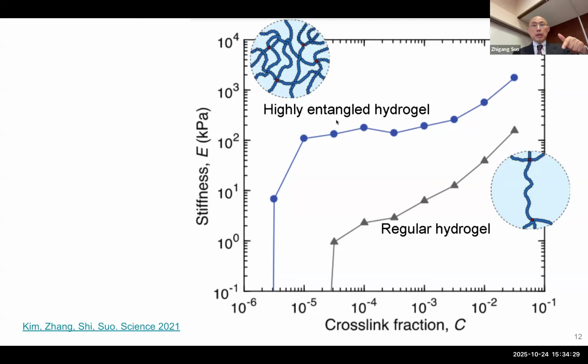Because when you have lots of entanglement, the modulus is dominated by entanglement. Adding crosslinks doesn't change modulus. You only change modulus when the number of crosslinks overtakes the entanglements. So that's our evidence, about 100 entanglements per crosslink. Okay, so we're very proud of this.